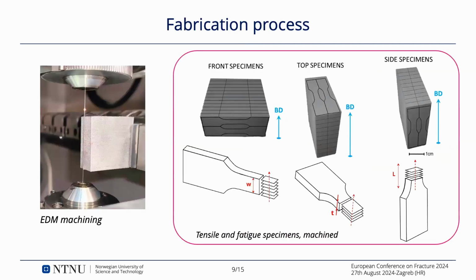And the reason to print these cuboids is to obtain different types of specimens. So we machined the specimens from the cuboids using the EDM machine, and we obtained front, top, and side specimens, changing the extraction direction and the orientation of the cuboids. So what is the difference? The front specimens have the layers that build up through the width. Then the top specimens have the layers that build up through the thickness. And finally, the side specimens have the layers building up through the length.